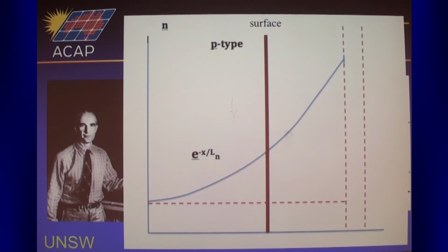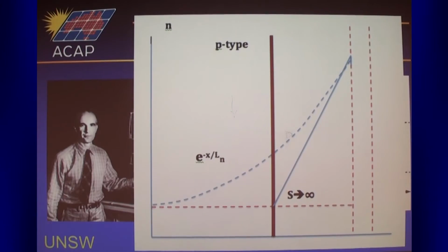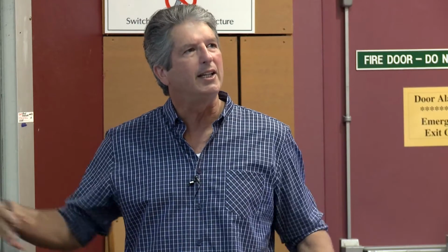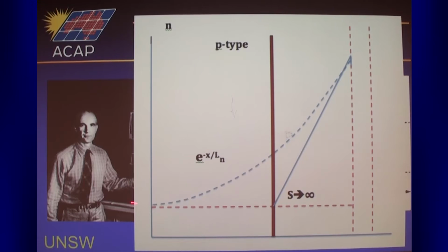So you stick a surface like that. And it depends very much on the properties of the surface. If you have a really bad surface, if you scratch the surface with sandpaper or something, you can get a really bad surface. And that gives you what's called an infinite surface recombination velocity. Any minority carrier getting to that surface is instantly gobbled up. So it means that you can't maintain an excess of them. If there's any carriers there above this equilibrium value, if there's any excess above that, they just get gobbled up infinitely quickly if you've got an infinite recombination rate.